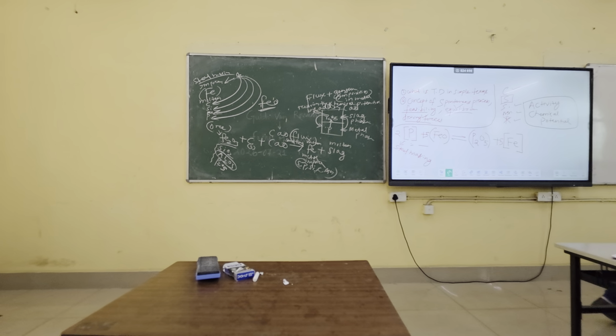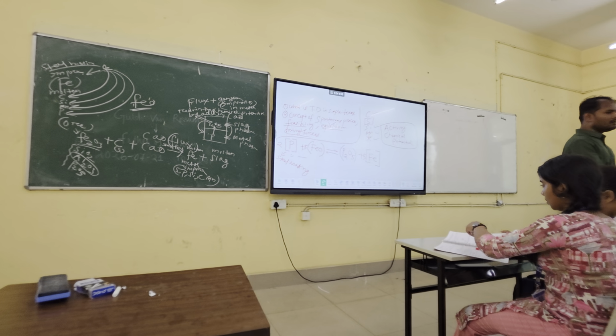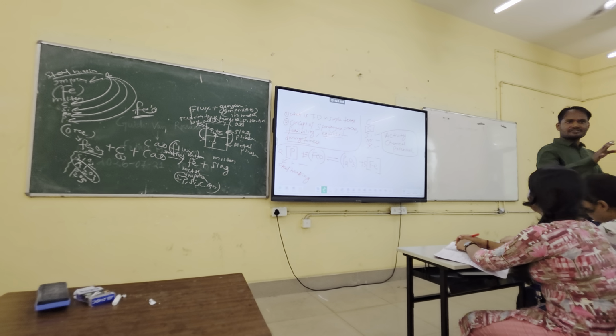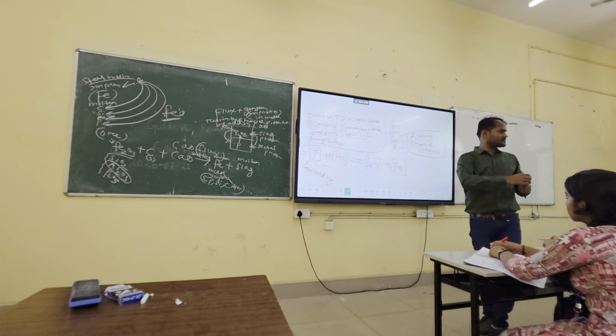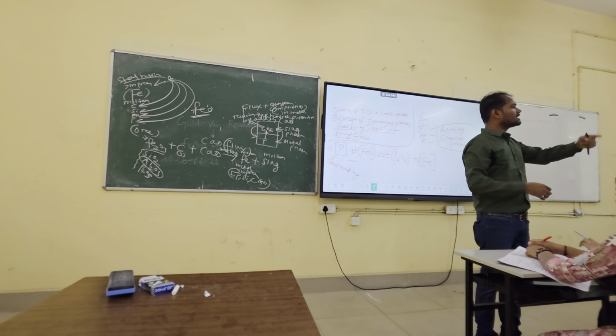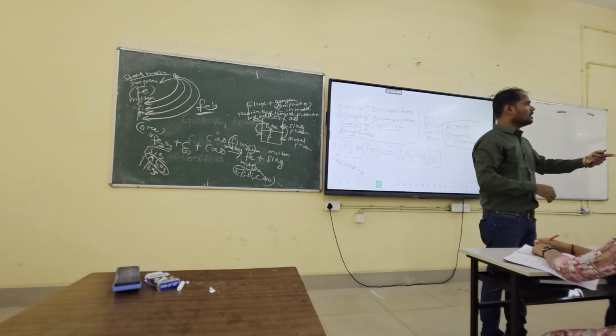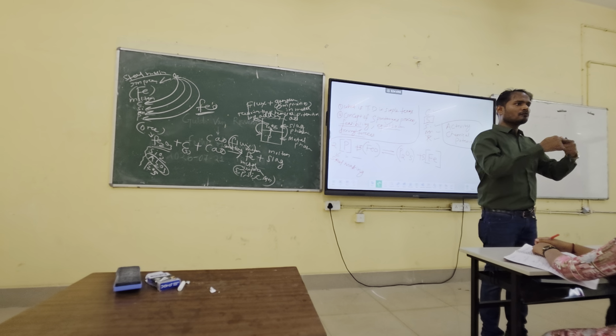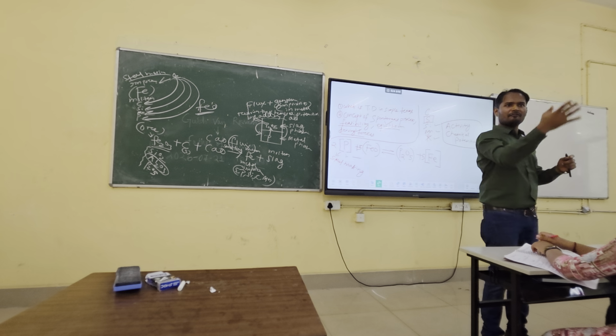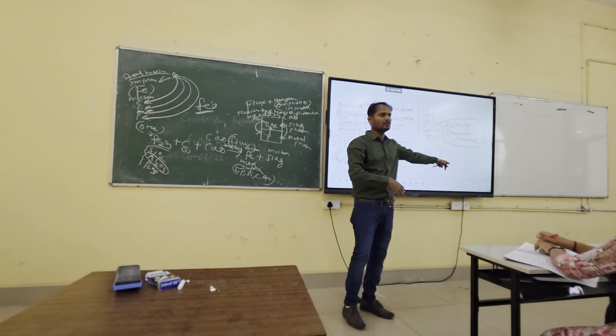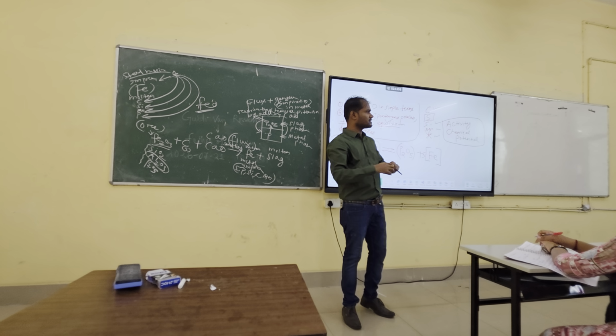Again let me tell you quickly. Initially you have impure iron, you want to make steel. That process is an oxidation process because we are providing oxygen, right? So oxygen will directly react with phosphorus to form P2O5. Now phosphorus has become an oxide, so it will migrate to the slag phase. So a lot of phosphorus is removed now. Also some FeO will be forming. That FeO also reacts with phosphorus to form P2O5. Again a lot of phosphorus will move to the slag phase.